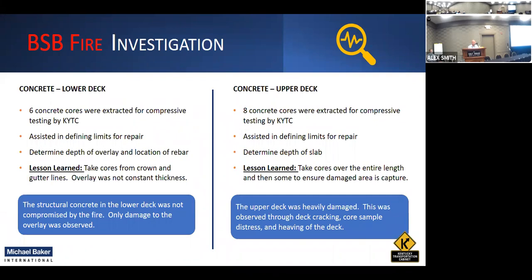So yeah, lower deck, we took 6 cores. That assisted us in defining what the limits of that heat affected zone was. But it also helped us determine the depth of the overlay, location of the steel in the deck. And one of the lessons learned from those concrete cores, we took cores right down the center line, and looking back, we probably would have wanted to take some along the gutter line, because that overlay thickness did change toward that gutter line. It wasn't a constant thickness.